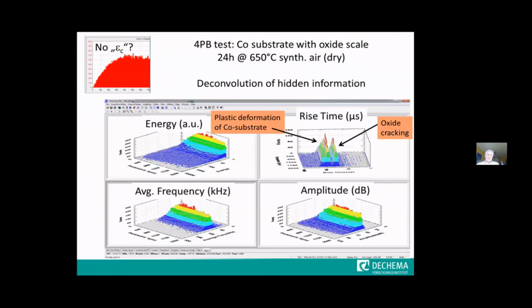And it's not always that easy as it was shown in that slide. It can sometimes happen that the acoustic signals from the oxide are superimposed by signals from the substrate. And this is something which you can see here for the example of cobalt oxide. In this case, it's necessary to do some more detailed analysis of the signal. If you do rise time analysis of the signals, then you can separate the two effects here. And by separating these effects, you can measure the critical strain of the oxide, and separate this effect from the other superimposed effects from the plastic deformation of the substrate.